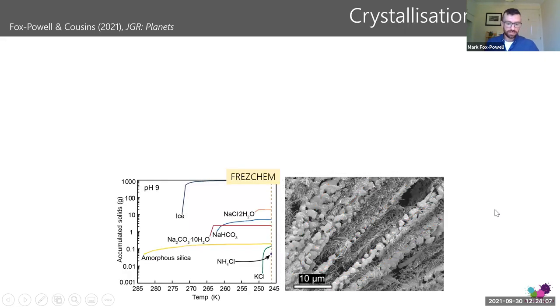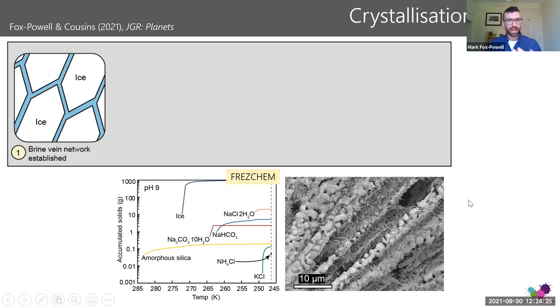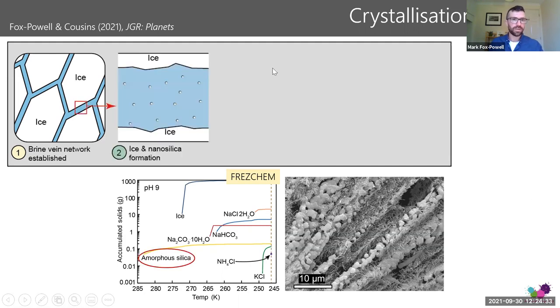So to try and explain that, we turned back to our thermodynamic models that we ran initially, and by comparing our analytical results with these models, we can understand the provenance of these crystalline materials. So first of all, we have ice forming. Alongside that, likely is precipitation of amorphous silica, which forms colloids. And these effectively form a suspension within the brine veins. This is a solid colloidal crystal suspension within the brine veins.